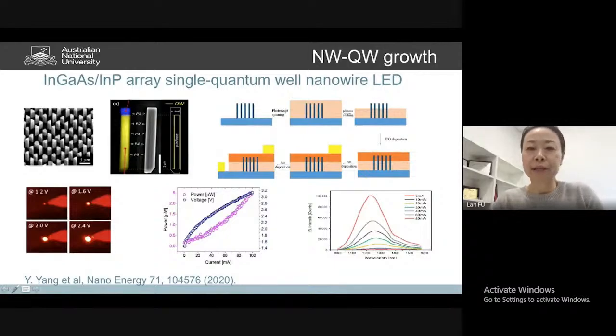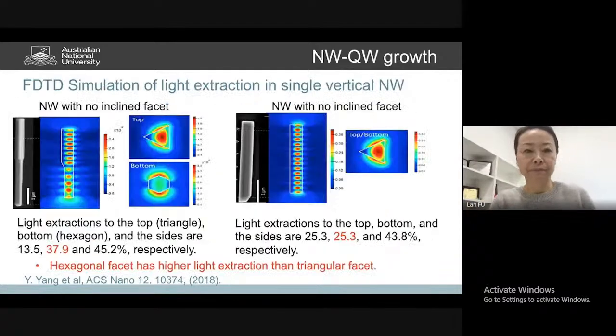So what we do is that we planarize the sample and make contacts on top and the bottom of the nanowire array, and thereby we can inject current. So you can see this bright light coming from the nanowire array. And this is infrared light. And of course, you can see that we have quite nice light coming from the whole array, which is about 200 micron by 200 micron in area.